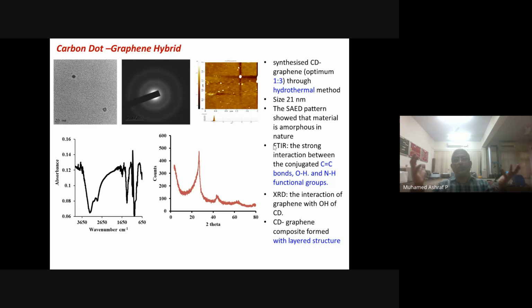Earlier we were all talking about nano copper oxide and nano titanium dioxide. People were very worried because it is an inorganic material, and we used to say that it will become a problem after some time. Then we thought of using only carbon dot and graphene. Both are carbon-based materials, highly degradable, and have less toxicity. And we synthesized this through the hydrothermal method.